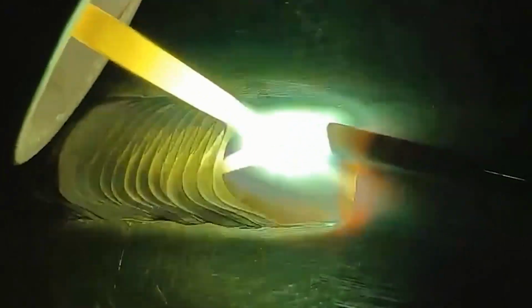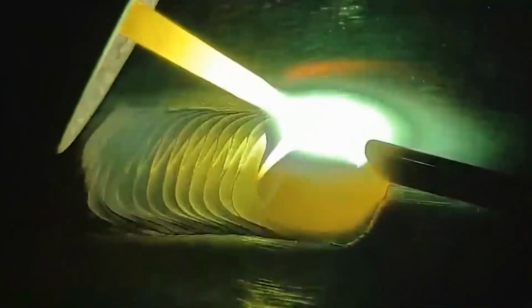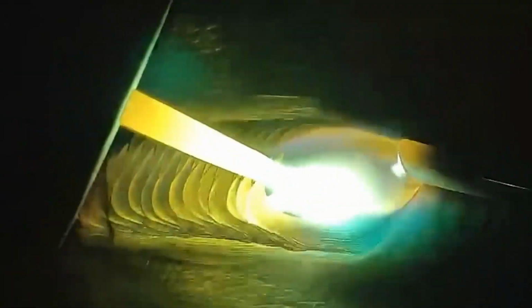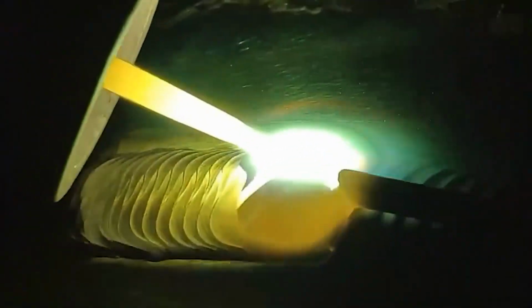Before manual arc welding is used, the weld groove should be covered with asbestos cloth within a range of 100 mm to prevent splashes from contaminating. The welding procedure specification should be strictly implemented in accordance with the welding procedure card. It is advisable to adopt the welding method with small current, short arc, small swing and small input energy. It is strictly forbidden to start an arc on the surface of the welded part, test current or weld temporary support. After inspection of the root layer is welded by argon tungsten arc welding, the secondary layer can be welded until it is completed after passing the self-inspection.